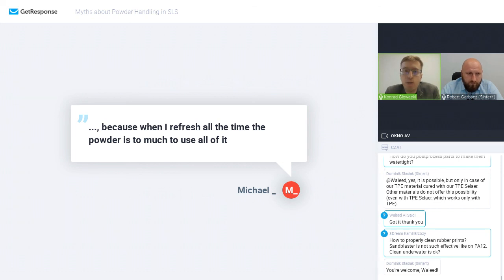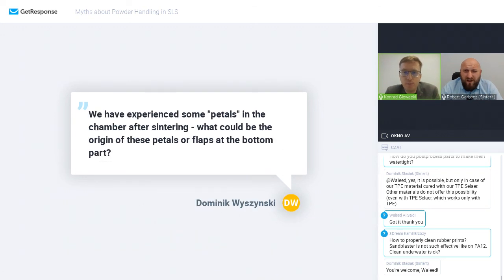As Robert said, you can print with this, and as soon as you see that it's not enough quality for you, just stop using it. The powder will be a little bit brownish. If you observe that after 3-4 times the powder starts to be a little bit brownish, just throw it away.